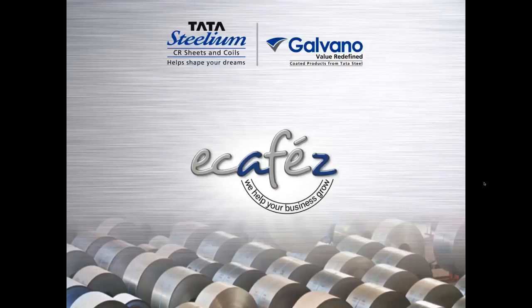We do not have blasting or power tool facility. We are using 3-in-1 chemical. I've checked the cross-hatch test. Adhesion is pass. So is it good to use 3-in-1 chemicals before priming? Mr. Mohit Wagela. Mr. Mohit, basically, in case of high-end corrosion resistance, only the cross-hatch test is not sufficient. We are doing one more test, called the adhesion pull-off test, where we press the dolly and pull it with hydraulic force and check how much hydraulic force it passes or fails. That is a slightly more stringent case, and if you need to improve, I think 3-in-1 will not give you the right pull-off test result as well. So this can be thought upon. Okay.